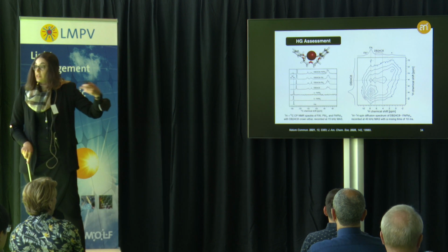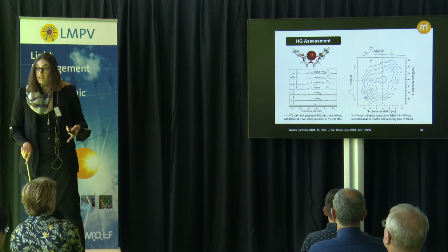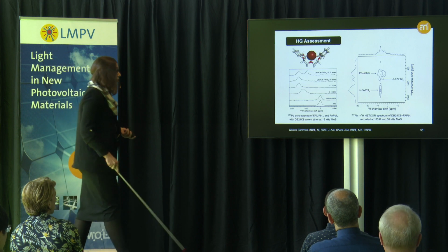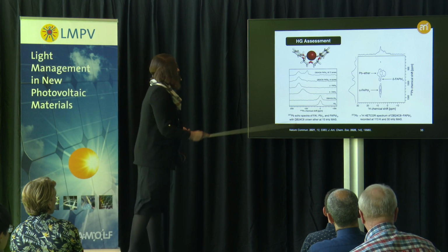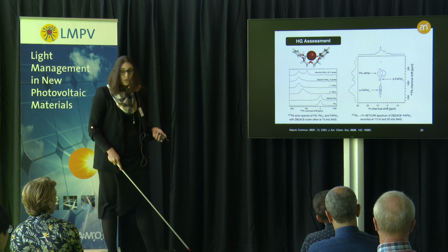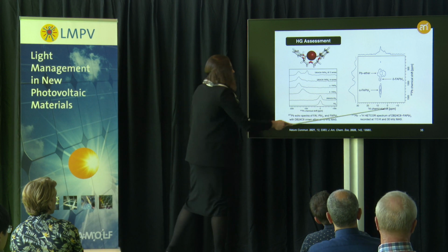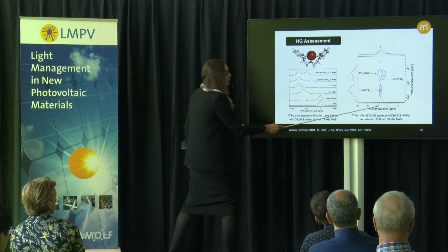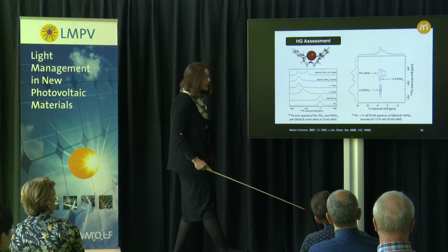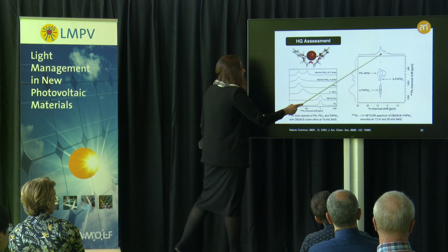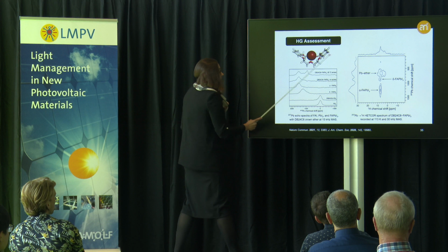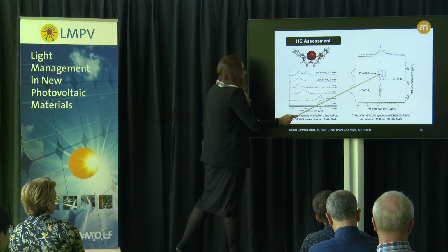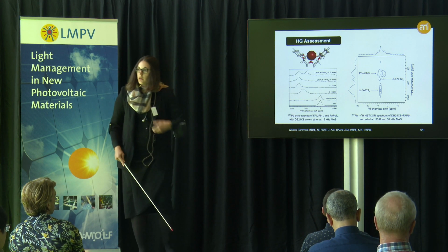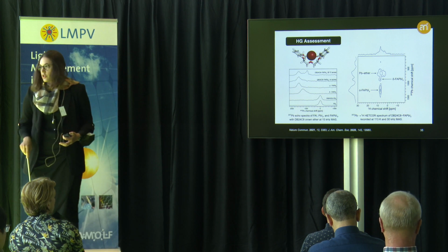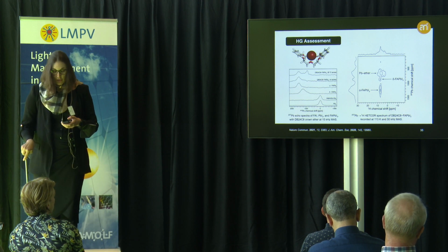And this can be done with a number of different nuclei to identify these species with confidence, including lead NMR, for example, for lead cation binding, including both the one-dimensional NMR spectra and the two-dimensional, in this case now, heteronuclear proton-lead heteronuclear coupling, where we correlate the proton environments of the host to different lead species, identifying their presence within the same phase, enabling us to assign these interactions to this particular binding of the species.